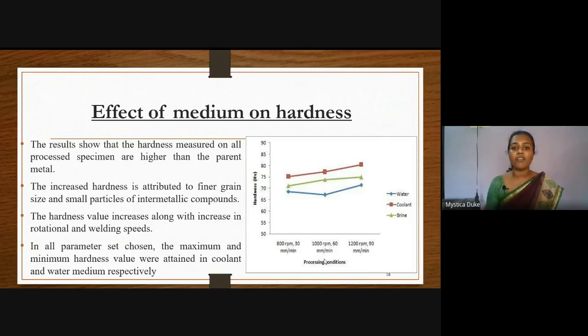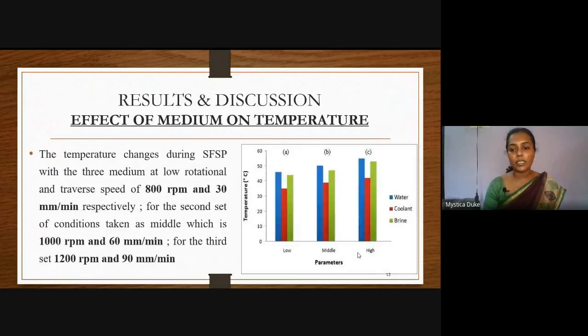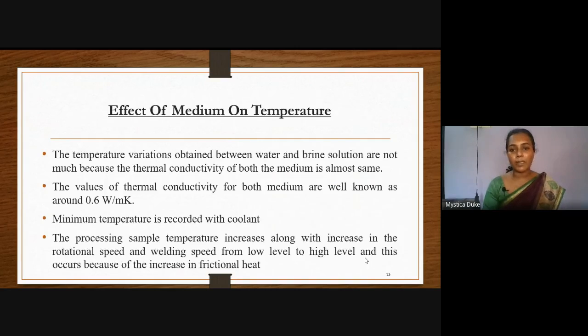Next, we found out the effect of these mediums on hardness. We found that the hardness kept on increasing with increase in the parameter combination. This happened with temperature also. Here you can see that with increase in the parameter combination, the temperature also kept on increasing. This is because with the increase in rotational speed, the tool tends to move much faster, so the frictional heat developed is also very high. Because of this, the temperature developed kept on increasing with increasing rotational speed and welding speed. The same happens with hardness too.